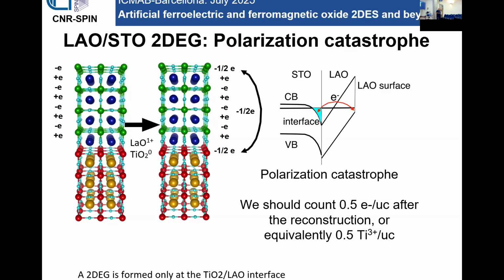So there are various ways to eliminate this polar instability and avoid the polarization catastrophe by, for example, chemical substitution, for example, disorder. But one mechanism that is certainly playing a role is the transfer of electrons from the surface to the interface, which means that the 2DEG is formed at the interface in order to solve the polar instability. It's not the only one playing a role, but certainly it's playing a role. And I would like to underline that a 2DEG is formed only in this case if the interface is titanium oxide, lanthanum oxide. A strontium oxide, aluminum oxide interface does not form a two-dimensional electron gas.